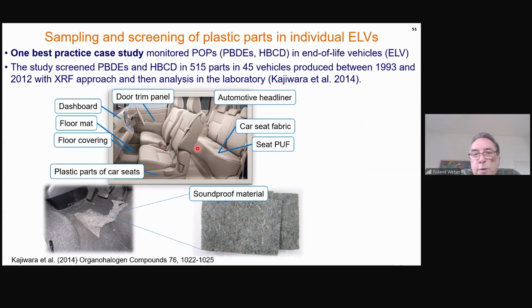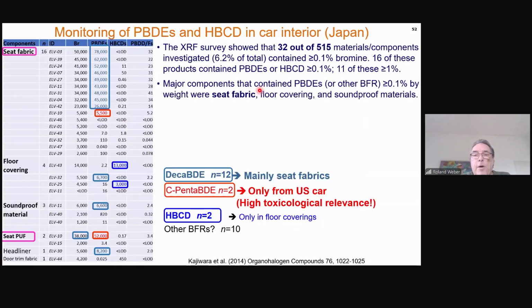That has been done also in Japan by Dr. Kashiwara. She analyzed 515 parts indoor of 45 vehicles produced between 1993 and 2012. Also, she used an XRF approach and then analyzed in the laboratory. What you see finally, the XRF screening showed that only 32 out of the 515 materials and components contain bromine higher than 0.1%, and only 16 of these contain PBDEs or HBCD above 0.1%. The major components were seat fabric. Actually, most of the highly contaminated PBDE materials were the seat textiles you are just sitting on when you are in your car, with direct exposure when you have shorts.